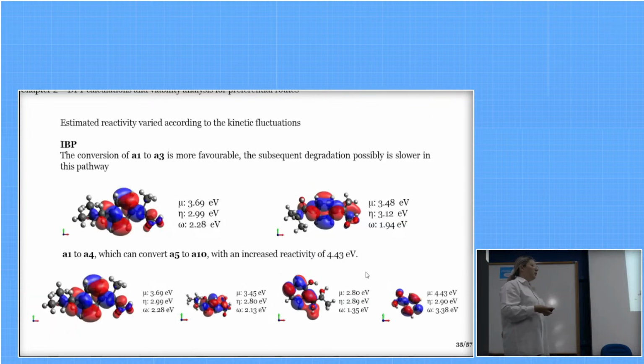Then we used quantum chemical calculations to estimate the reactivity of these fragments, where we show that for ibuprofen, the conversion of A1 to A3 was more favorable, and the subsequent degradation was slower in this pathway. So when the pristine molecule degrades to A3, the pathway tends to slow down. And when A1 converts to A4, it can convert to A5 and A10 directly. So the mineralization here is faster, with an increased reactivity when compared with these 2 first fragments.